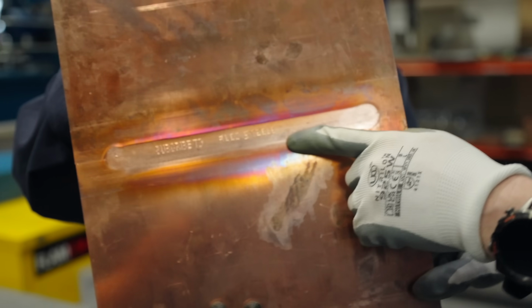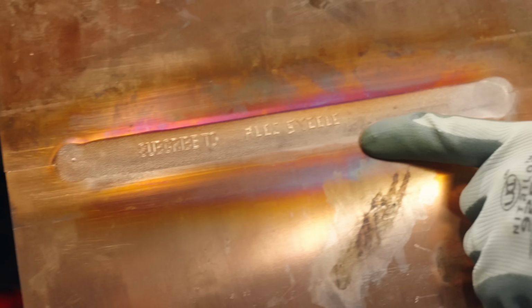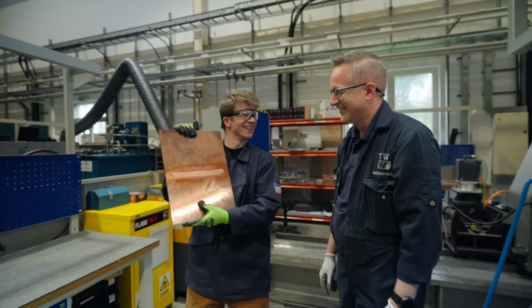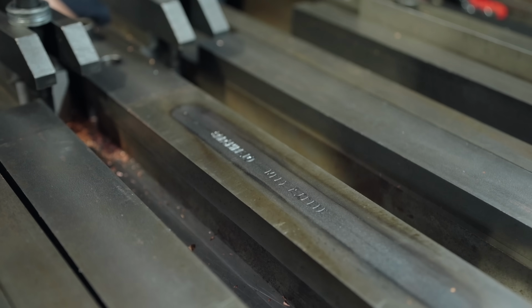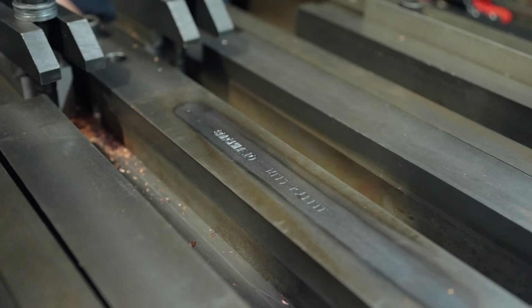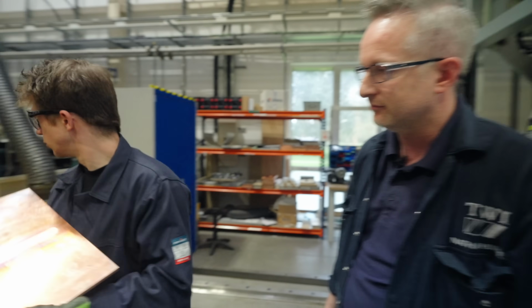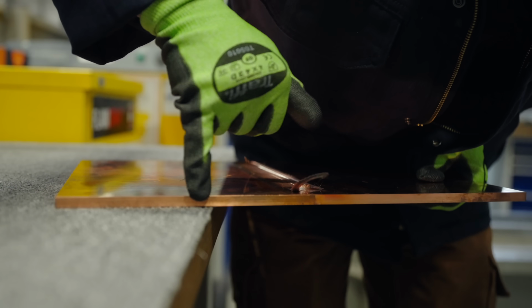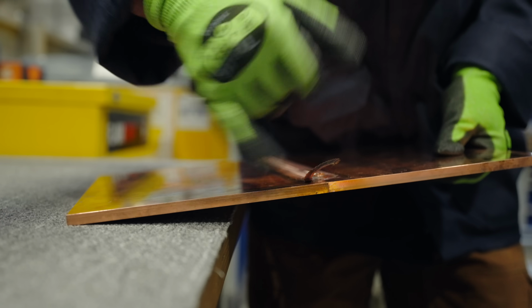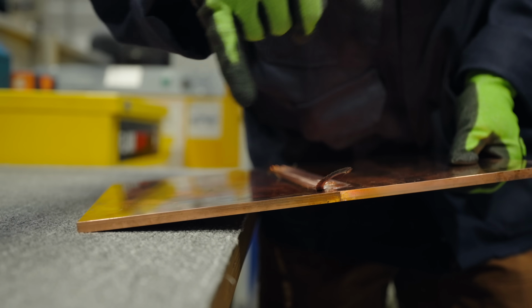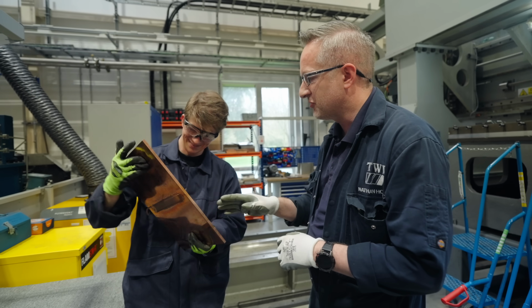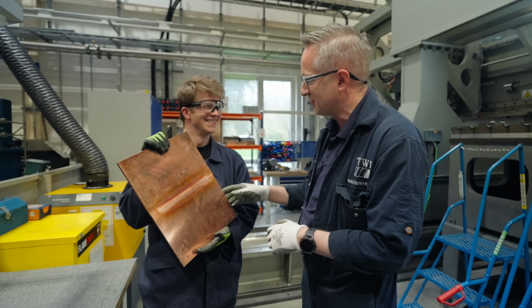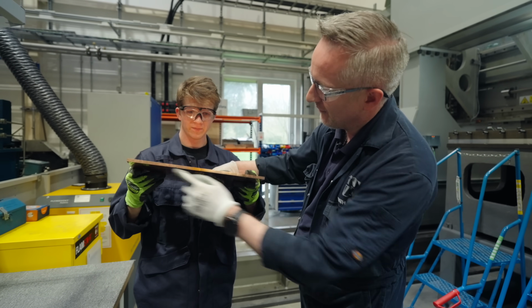How did you do that? That is outstanding. How did you put that in there? That's on the backing bar. How did I not spot that? So the bottom of that tool is just ever so slightly up from the bottom of it. Yep. It's still getting hot and it's still getting plasticized and stirring, even though the tool isn't all the way through. And yeah, as you can see, this is a low distortion process because these plates have not distorted.